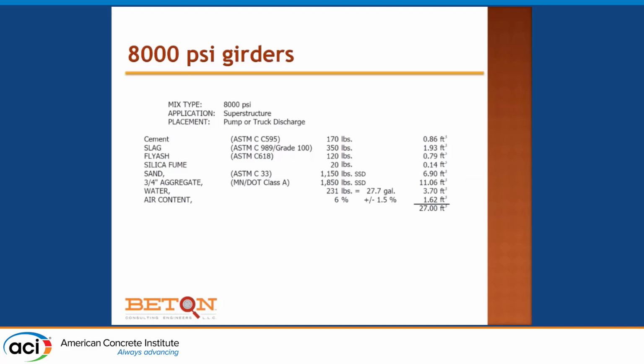We needed something to give us an initial set and early strength gain and heat, because we are activating the slag with heat. Those of you who are familiar with the chemistry of the pozzolanic reaction will notice that I am not using the slag at all for its pozzolanic properties, because by the time it gets reacted, the vast majority of the calcium hydroxide that has been produced will hopefully have been consumed by the silica fume.